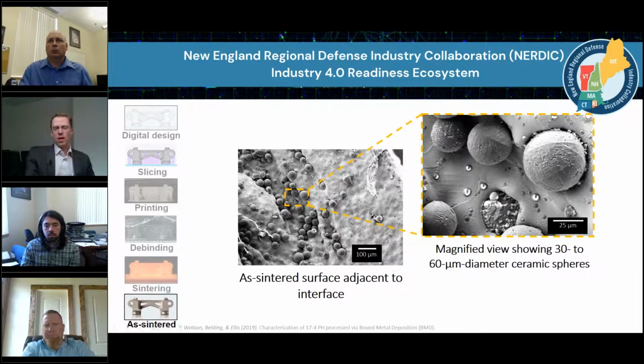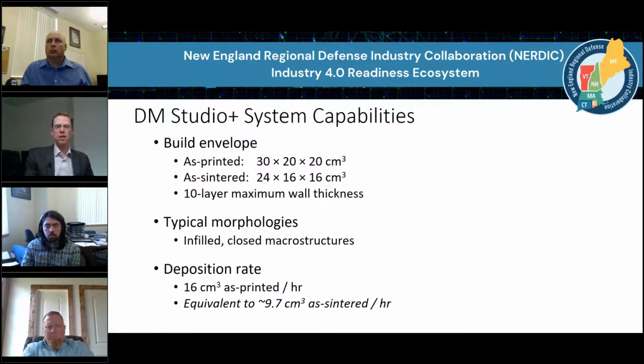If we look at the as-sintered part right at the interface, this is where we have the ceramic interface that separates the raft from the as-sintered part. Well, we can see there's these little ceramic spheres, and these spheres are what prevent the raft from sintering together or fusing together with the part. Kind of interesting. And now just a generic summary of where the system capabilities are.